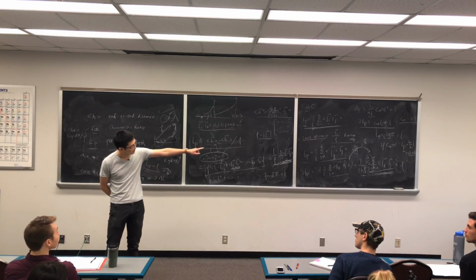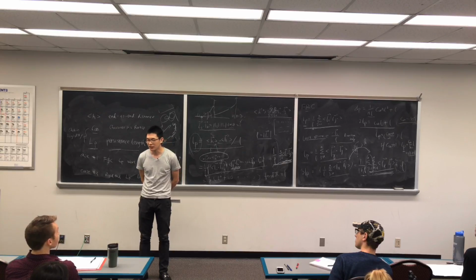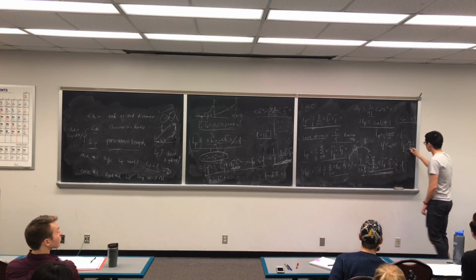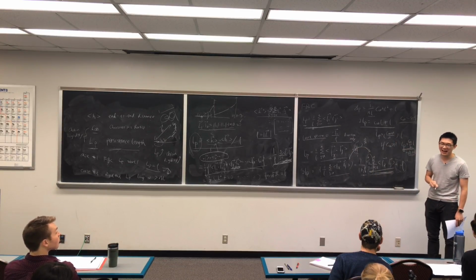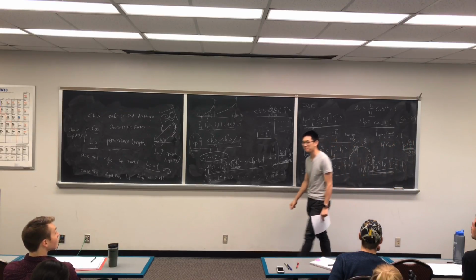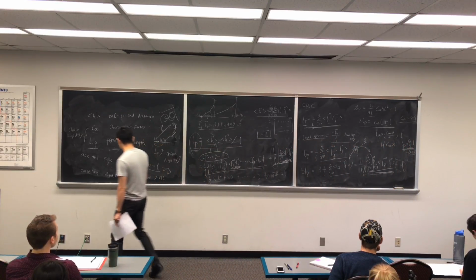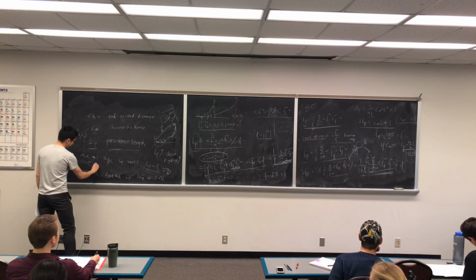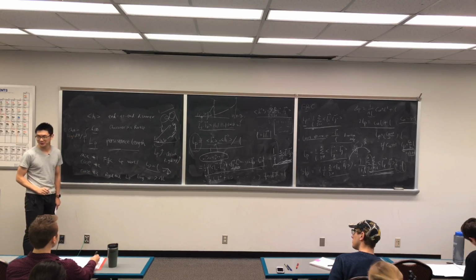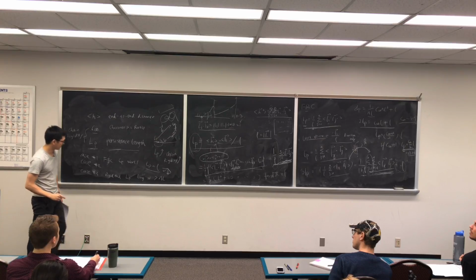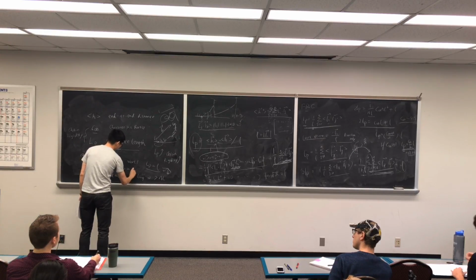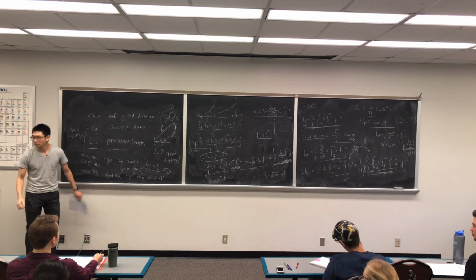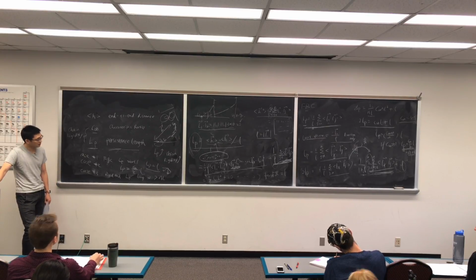So for these values, the key is you need to know this relationship: LP would be equal to half of C infinity multiplied by L. We went a long way there, but now let me put it here. Case 2 is, in a lot of cases, LP will be just equal to half of the characteristic ratio multiplied by L.